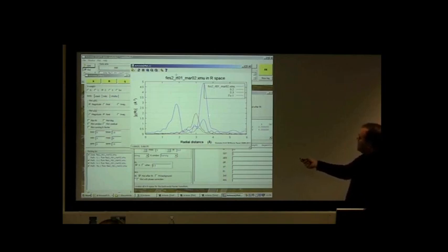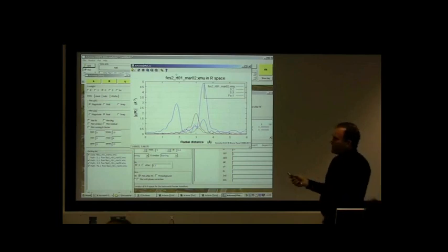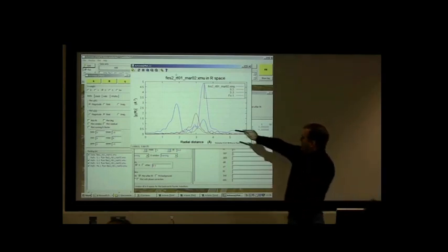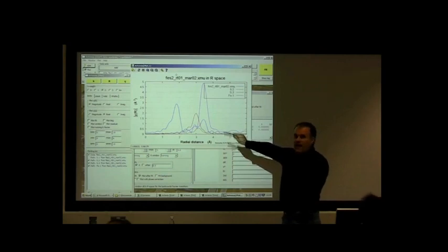The green overlaps substantially with the red, and the green overlaps substantially with the purple. And in fact, the red and the purple themselves overlap substantially. So the point I'm driving at is that, in short, the Fourier transform of chi of k is not a radial distribution function. You can't just point at a peak and say, that peak is an atom, and this peak is...